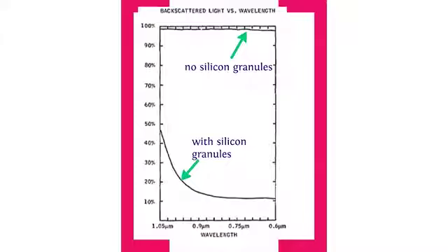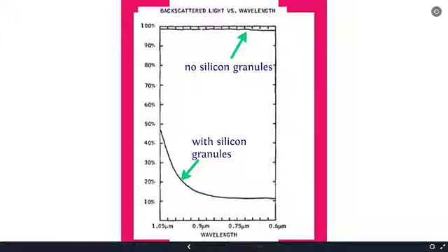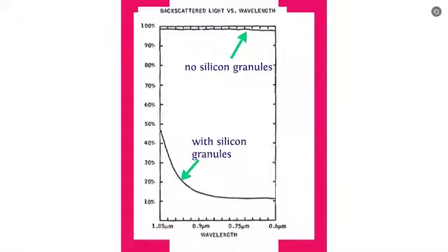In other words, roughly 20% of the area is covered by the silicon, but you're absorbing more than twice that in terms of light. So if you were to build a window by using a little bit of silicon, where you've saved cost, you're able to absorb some of this light and convert it into electricity, but you can see some of it passing through the window as well. So it'll be like a tinted window. This is an example. And that's my last slide, so I'll stop here.